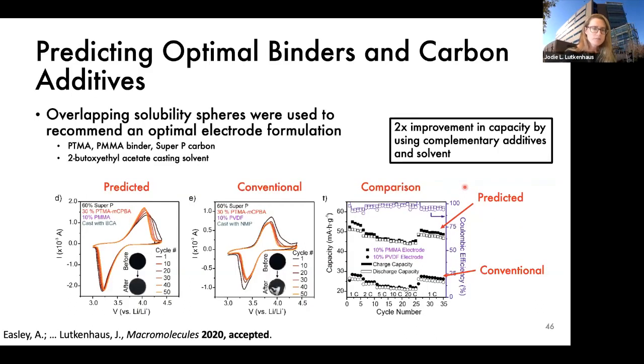Okay, and then moving along for that, because we now know the solubility parameters and the behavior of the polymer, we can then predict what the electrode composition should be and what the casting solvent should be. And we did that by looking at the solubility sphere projections for a variety of binders, the polymer and carbon additives, and then potential casting solvents. And we settled on this composition.